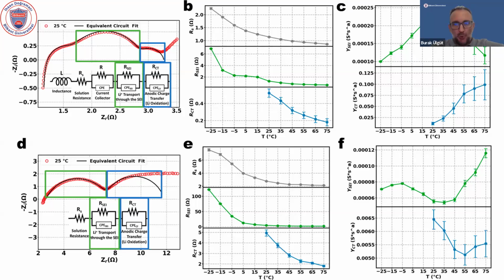One interesting point is the capacitances. What you're seeing on the right-hand side of the slide are the two capacitances that we are identifying as the salt electrolyte interface. Now, in the thionyl chloride case, capacitance goes up as temperature goes up, and then it appears to go back down. And then in the manganese oxide case, it is more or less flat up until 45 degrees, maybe a slight decrease, but then it starts going back up. So the nature of the SEI and dielectric properties of the SEI are clearly different between these two, even though they are both lithium metal electrodes.